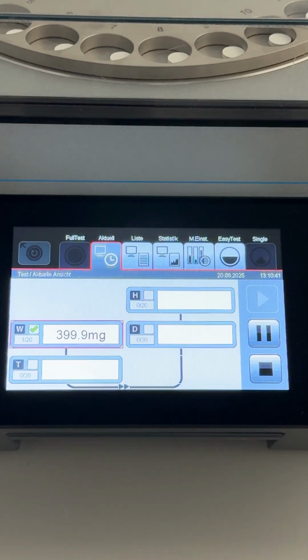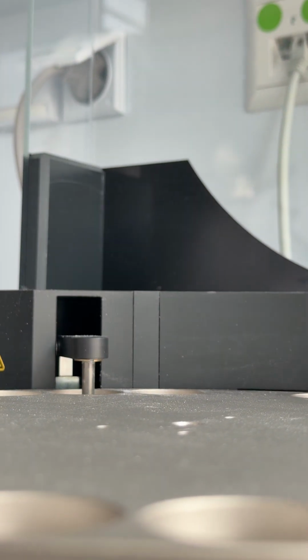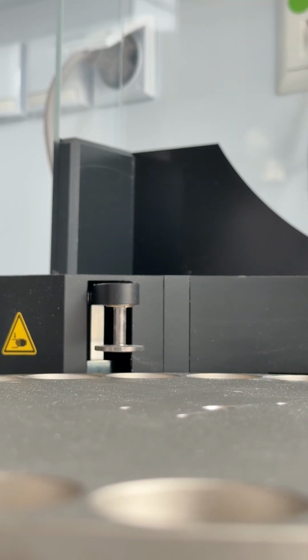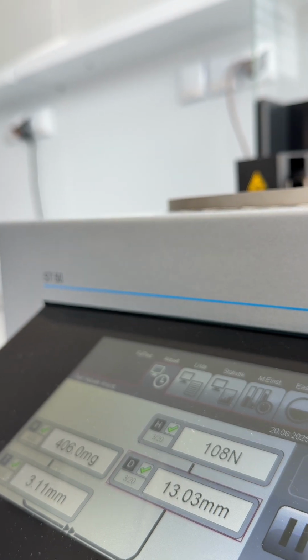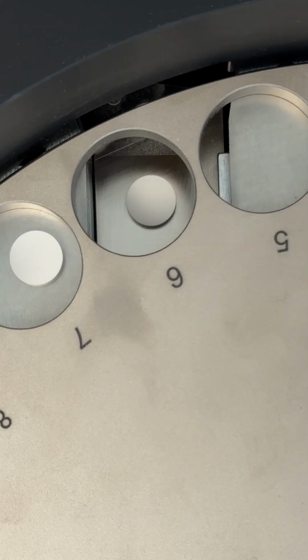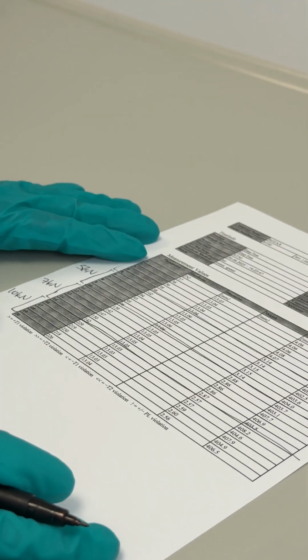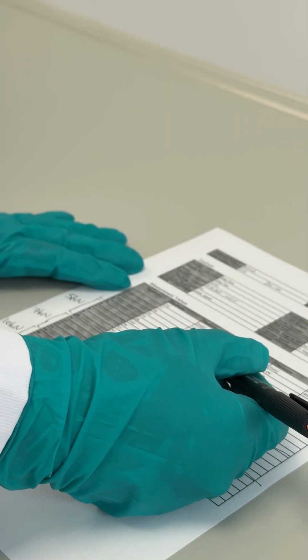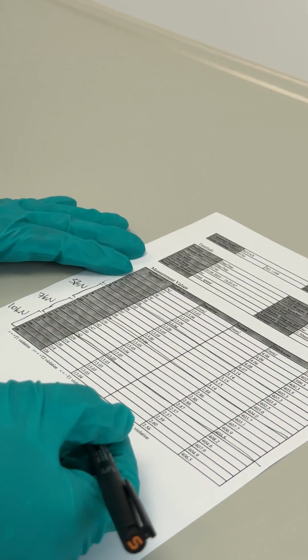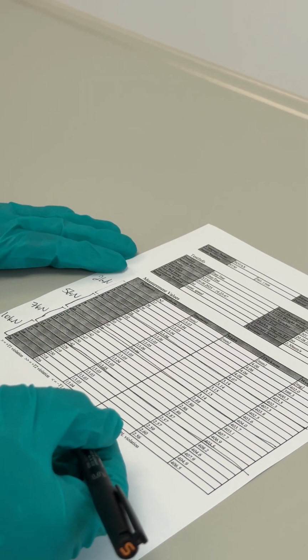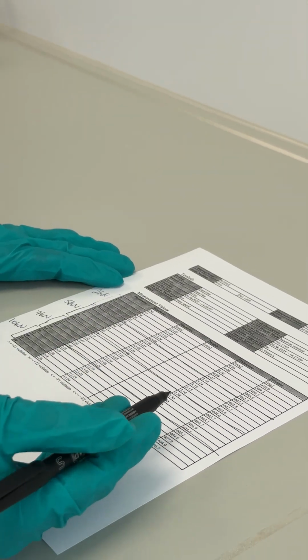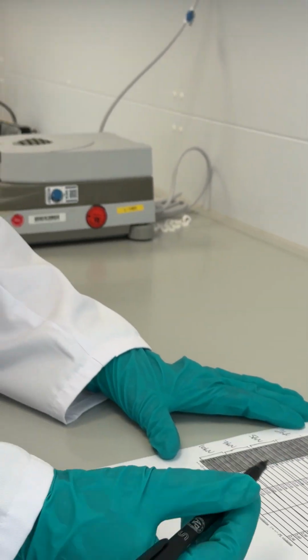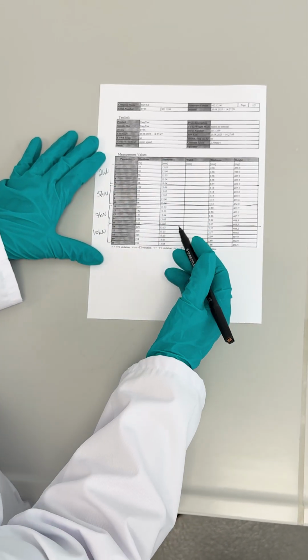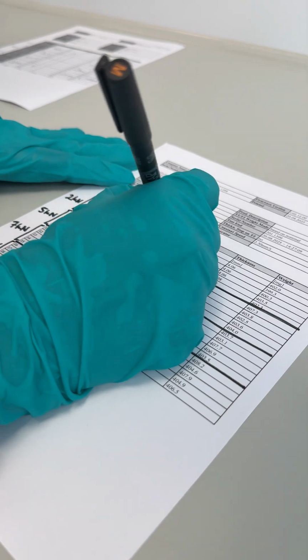can measure weight, tablet thickness, which you maybe can tell changes as the compaction force goes up, but then also the diameter of the tablets, and then finally the breaking force of the tablets. I've got the tableting results here. So first, if we take a look at our diameter, in fact, there's really no change for any of the compaction forces. Our material's not particularly elastic, so this diameter is set mostly by the hole in the die. So that's just 13 millimeters.